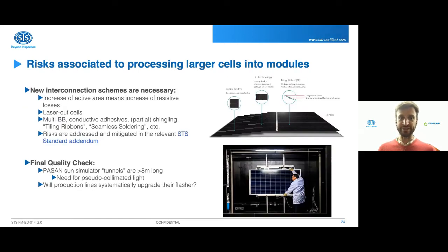Now, if you look at the next step, so from cells into modules, you see that when you're bringing more cells, larger cells, you run into a problem. You absolutely don't want to increase the voltage. Actually, most of the new modules have, if anything, a lower voltage than the traditional ones, because you want to put as many modules on one module string as possible to reduce the balance of system costs. But then, if you increase the wattage and you cannot increase the voltage, then you have somehow to increase the current, and that is exactly what a larger cell does. So you have to have ways to mitigate the increase of currents coming from the cells. And that comes from cutting the cells, sometimes in 2, sometimes in 3.